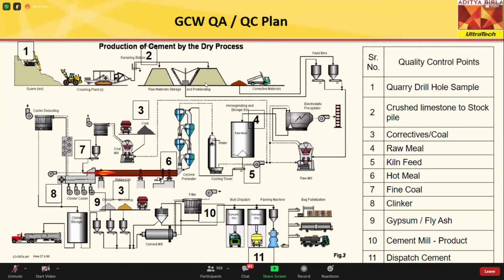This material, that is limestone, and the corrective material like bauxite and iron ore are taken to the hoppers of the raw mill, and a judicious mix of these materials is fed to the mill where it is ground, and around 13 to 15% on 90 micron and around 1 to 1.5% on 212 micron sizes is maintained. This is continuously monitored, and accordingly the process team takes action to control the process.